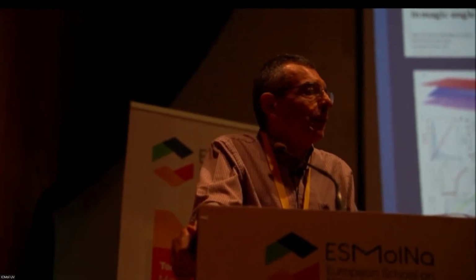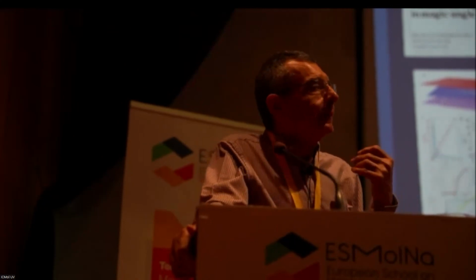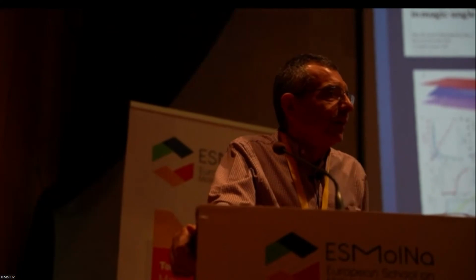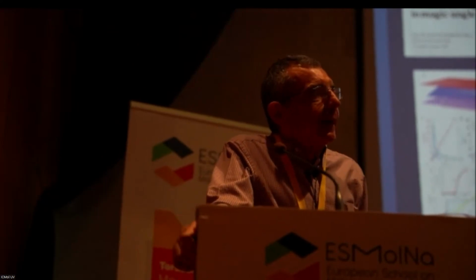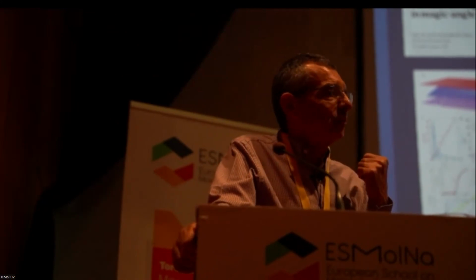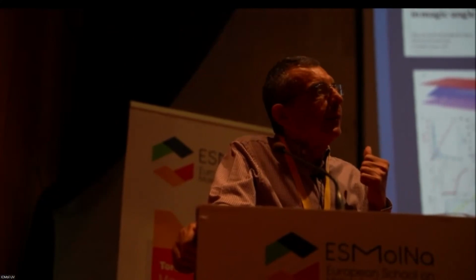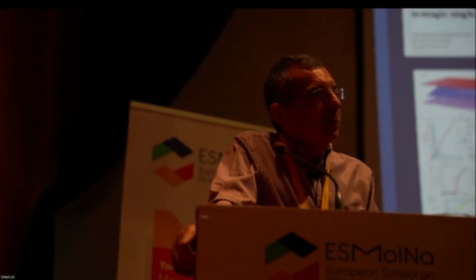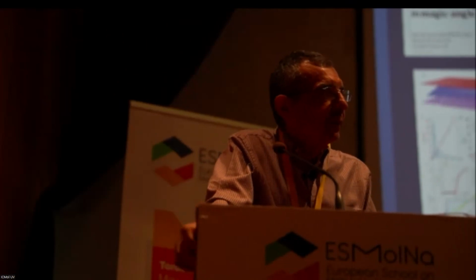No, nobody knows. I have worked, for instance, on the shapes of bubbles, which are always there, and they're supposed to be hydrocarbons inside the bubbles. I was told by experimentalists that these things have bubbles, with some kind of dirt inside. What the bubbles do is a big mystery. Of course, all these samples are encapsulated. Actually, there's very little evidence, if any, of superconductivity in the samples they use for STM experiments, which by definition cannot be encapsulated. So encapsulation maybe takes care of some of the contamination you may have. But to tell you the truth, nobody knows very much. People are happy that the systems have superconductivity, and nobody has paid a lot of attention to those issues.